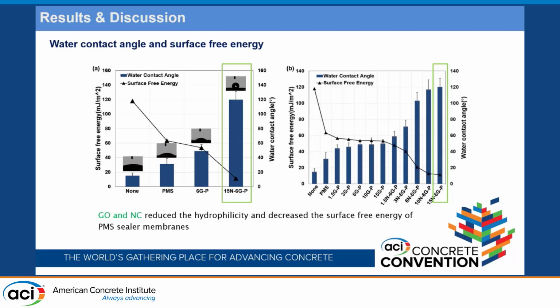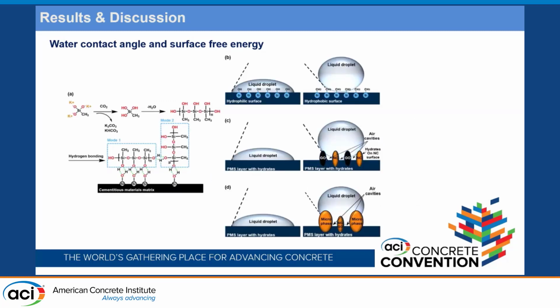characterize the surface property. As we can see from these two figures, after adding nanomaterials into the sealer, the water contact angle increased. That means graphene oxide and nanoclay will increase the hydrophobicity of the surface. And this figure shows the possible mechanism of this enhancement.